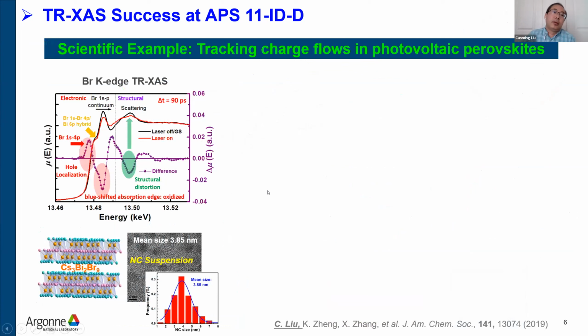Okay, now I'm going to show you concrete scientific examples demonstrating how we apply TR-XAS techniques to track the charge flows in lead-free bismuth perovskite nanocrystals. Here are the nanocrystal samples. This figure shows how we get the TR-XAS spectrum. It is obtained from the difference between the laser-on and laser-off X-ray absorption spectra.